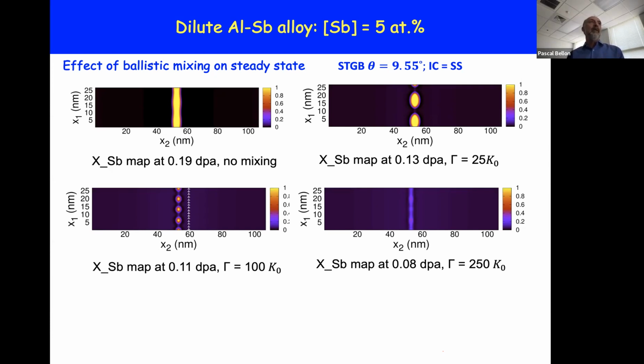Yes. There's another attempt that we made where we included that coupling directly, using the model from Fadi Abdeljawad and Stephen Foiles, where the grain boundary is represented by a grain boundary phase. That phase is captured by another parameter that evolves with the Allen-Cahn equation. In some cases, we couple both the conserved and non-conserved fields, and then you would see motion. The grain boundaries may move and drag the precipitates behind them. So there are all sorts of intriguing coupled evolutions that can happen. And you're right that Professor Abhinandan and his collaborators have worked on that.